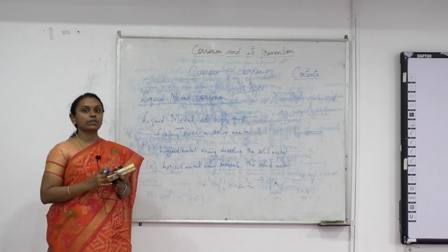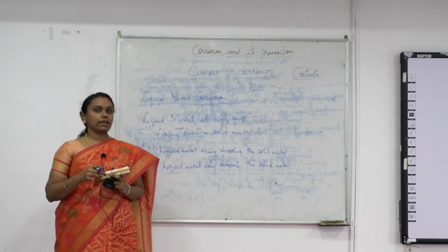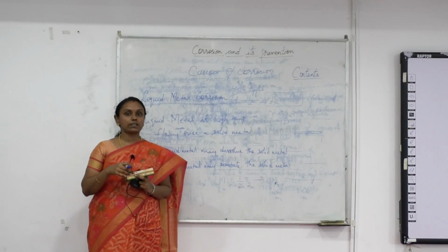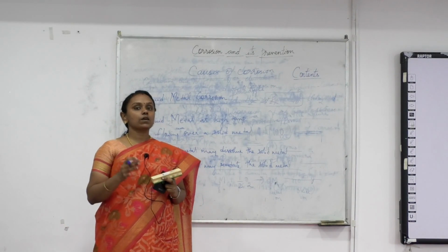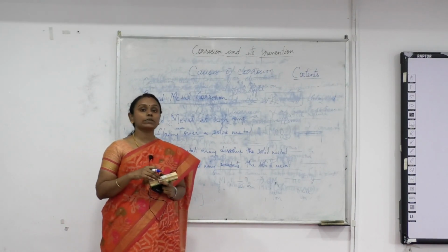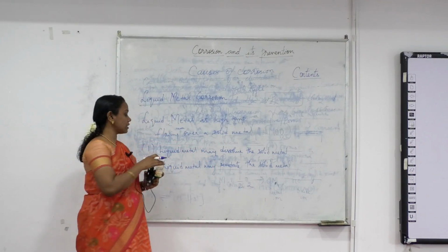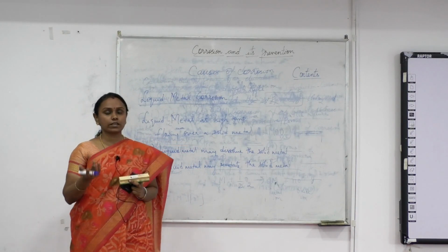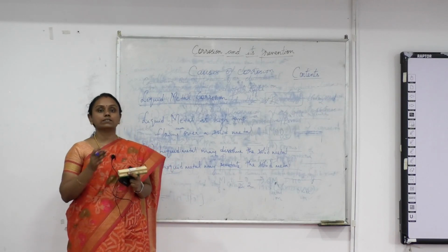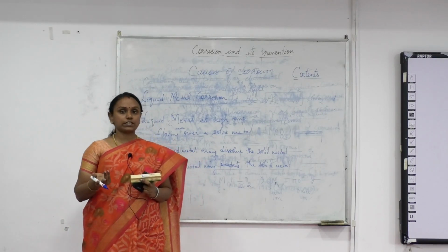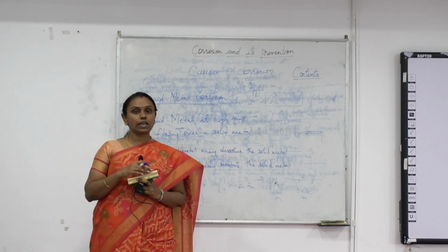In the direct attack of oxygen on metal, the first step is formation of a metal oxide layer. Then depending upon the nature of the metal oxide layer that is formed, further corrosion can take place or corrosion can stop in the initial stage itself. The metal oxide layer that is formed can be of 4 types. If it is stable, that means it will not lead to further corrosion. Then it is protective in nature. It is non-porous and tightly adhering. Metals like copper, tin, lead and aluminium will form such stable metal oxide layers.